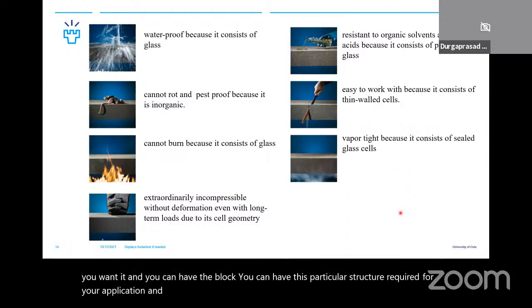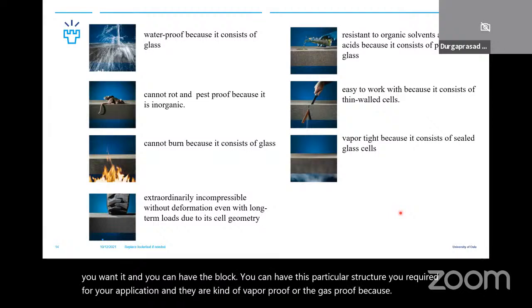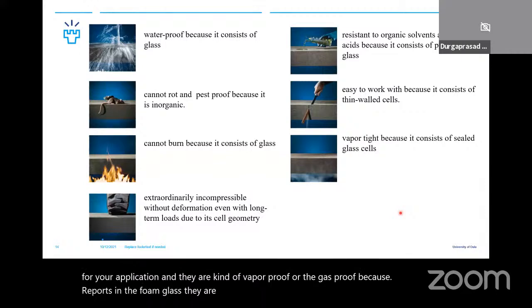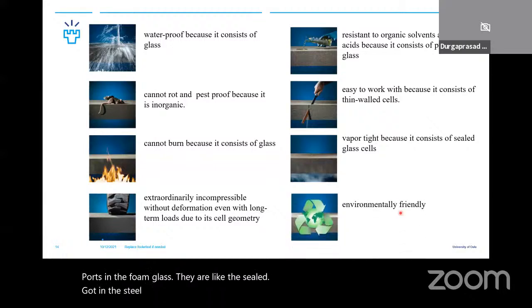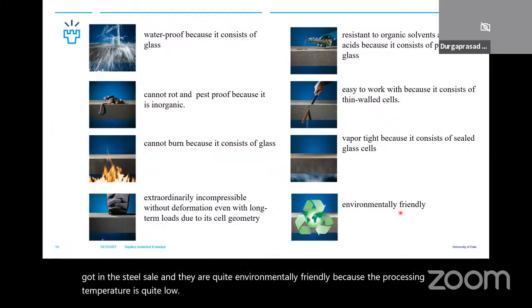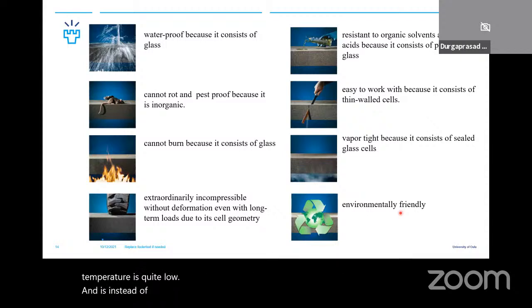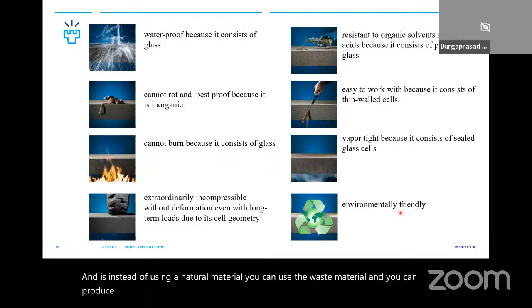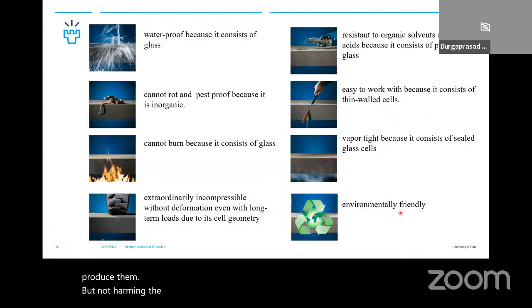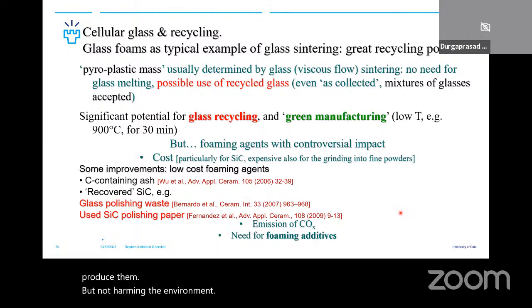And these are vapor proof or gas proof because the pores in the foam glass are in a sealed cell. They are quite environmentally friendly because the processing temperature is quite low, and instead of using natural material, you can use waste material and produce them without harming the environment further. So it's basically a cellular glass, and it can be made by recycling glass.